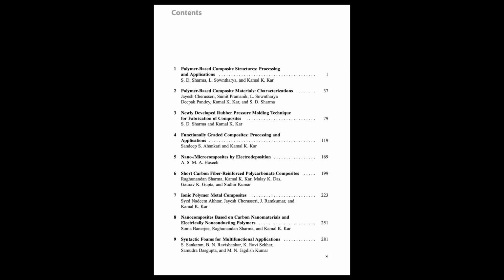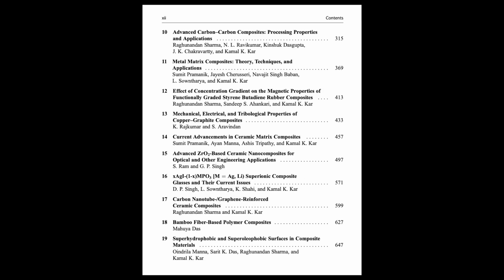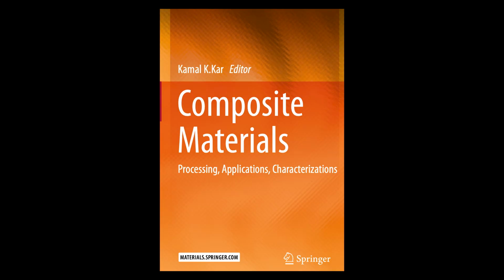How do engineers predict stiffness? Well, simple models like the rule of mixtures help. Equation 2.36 predicts stiffness along the fibers. And for many polymer composites, the fibers are way stiffer than the matrix. So the fiber properties dominate. Pretty much. E1, the longitudinal modulus, is roughly the fiber modulus times the fiber volume fraction. For stiffness across the fibers, the Jones model is simpler, assumes equal stress, ignored some effects.